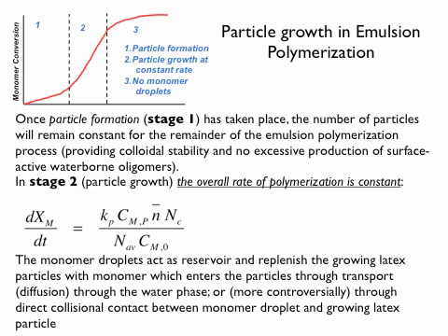That's the overall accepted way transport happens. A slightly more controversial idea is that there could be a collision between a monomer droplet and a growing particle, and then the growing particle can take up as much monomer as it wants. It could be a reversible collision, going back into the continuous medium. That's not in very many textbooks, but you could imagine it plays a role as well.